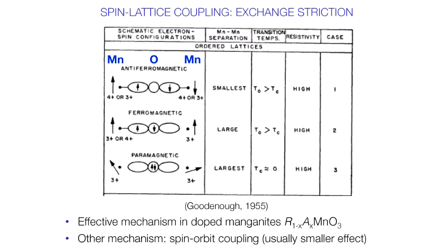Okay, so this mechanism is very effective in doped manganites, like this perovskite structure, where you have a partial occupancy of the A-site by a rare earth, this is why R, typically trivalent, and the alkali metal, typically divalent, because this changes the valence of the manganese ions.